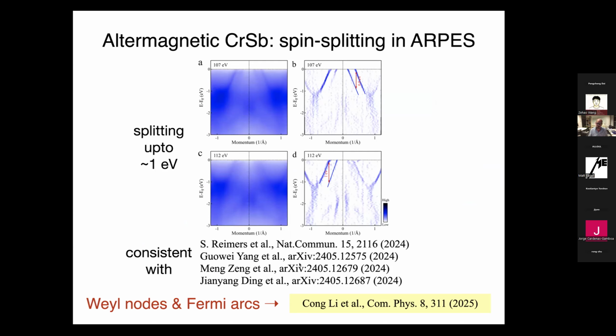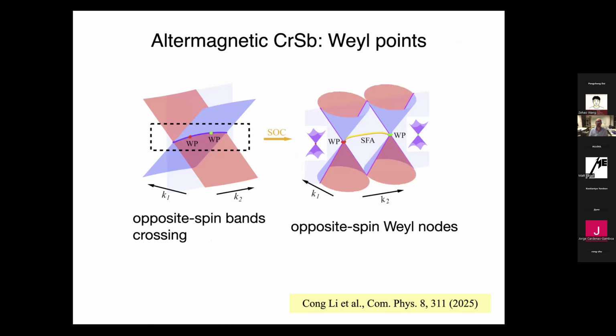What is different in our paper is that we pointed out that there are Weyl nodes in the system. These produce Fermi arcs, and these Fermi arcs we observed experimentally, or our experimental colleagues observed them. And just to give you one slide with a flavor of how this works. As I told you before, without spin-orbit coupling, at high symmetry lines or planes in momentum space, the bands are degenerate. So in an altermagnet, there are large portions, lines in momentum space, where the spin-up band crosses the spin-down band.